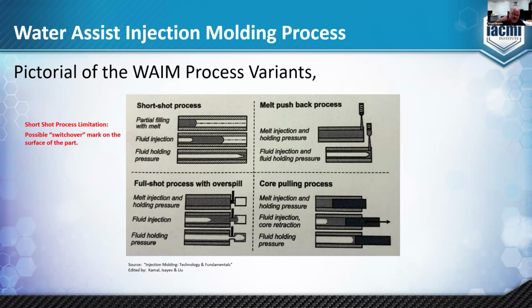The full shot process with the overspill cavity is in this quadrant. You see you're filling the cavity, you're injecting water, which pushes the polymer melt from the core into the overfill cavity. And then you're holding both with polymer melt pressure, pack pressure, as well as water pressure. In the melt pushback, you see that you're actually injecting the water at the end of flow, which is displacing the hot material from the core back into the injection unit. And then in the core pullback, you are injecting the polymer melt and then displacing the cores to create the volume that you can hollow out.